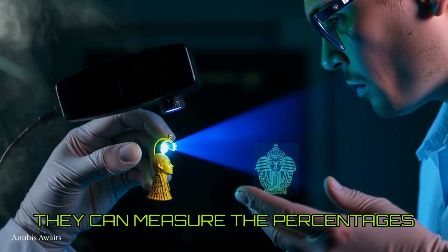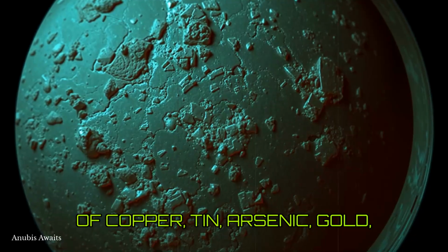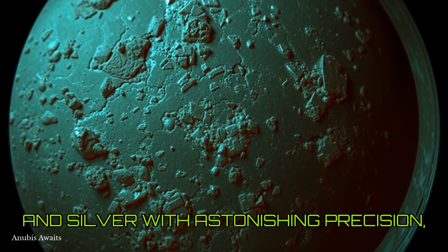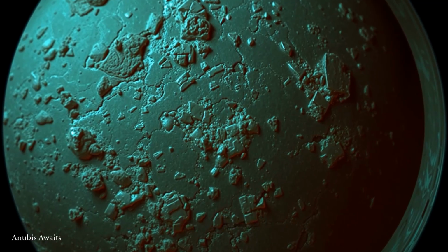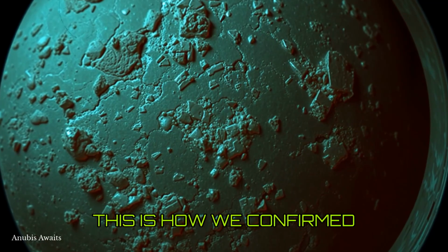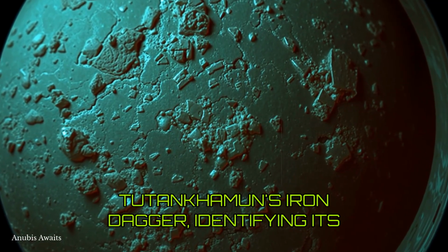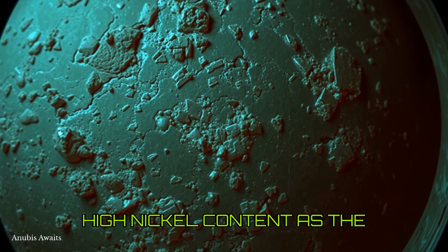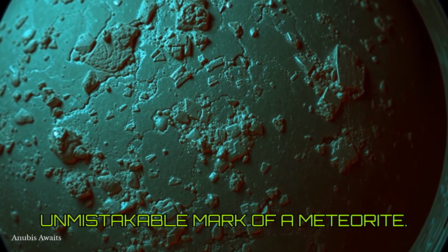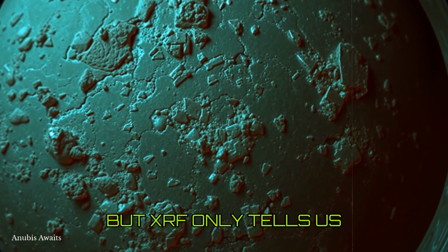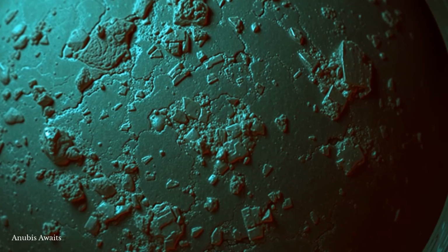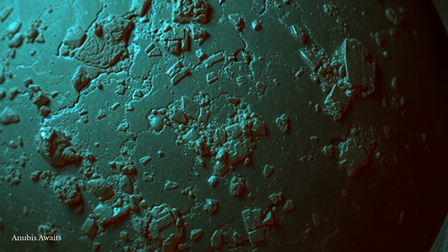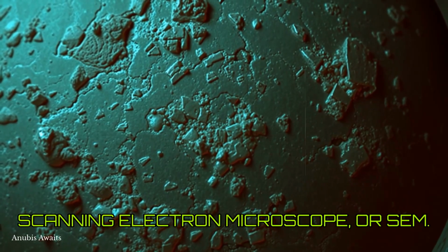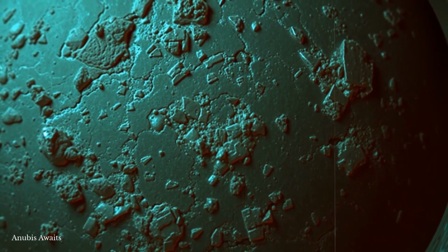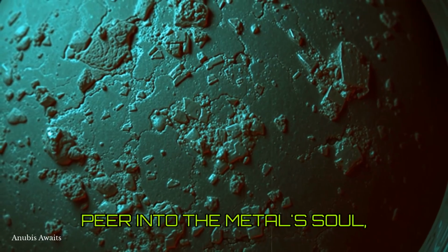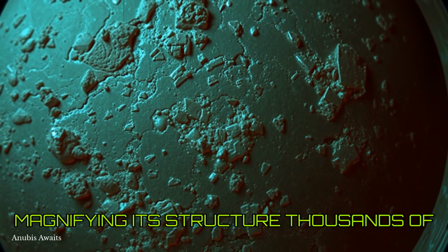the surface. They can measure the percentages of copper, tin, arsenic, gold, and silver with astonishing precision, revealing the ancient smith's precise formula. This is how we confirmed the celestial origin of King Tutankhamun's iron dagger, identifying its high nickel content as the unmistakable mark of a meteorite. But XRF only tells us what the metal is made of. To understand how it was made, we turn to an even more powerful instrument, the scanning electron microscope, or SEM. This device allows us to peer into the metal's soul, magnifying its structure thousands of times.